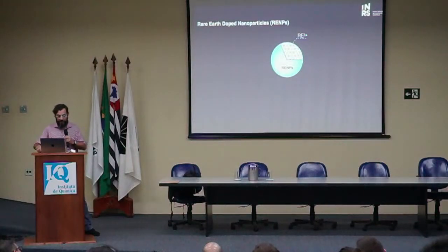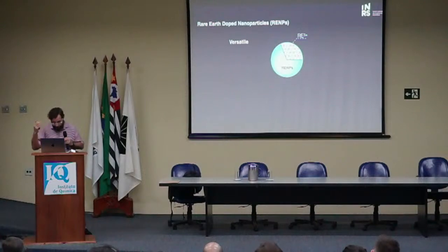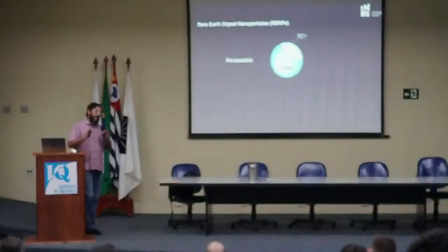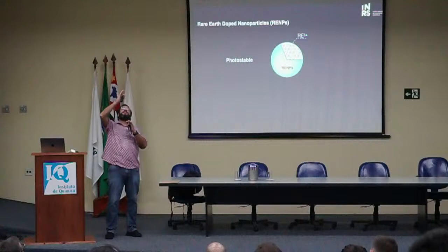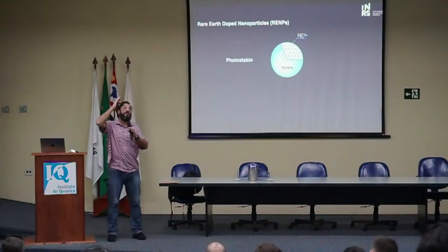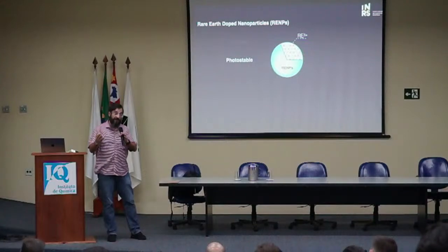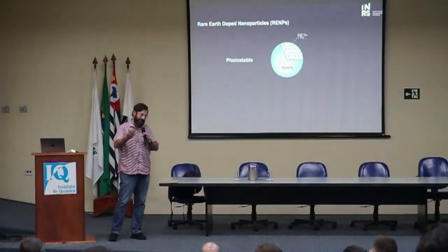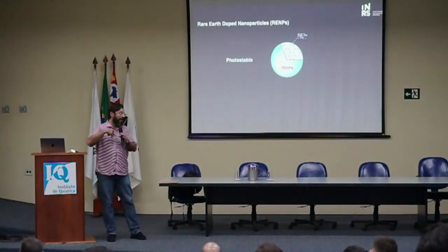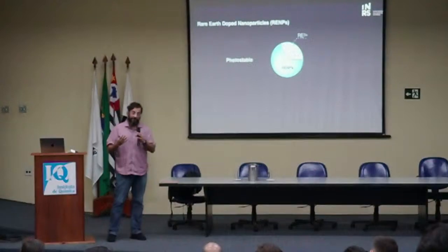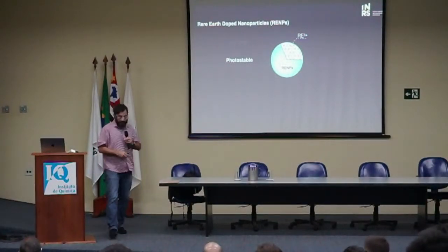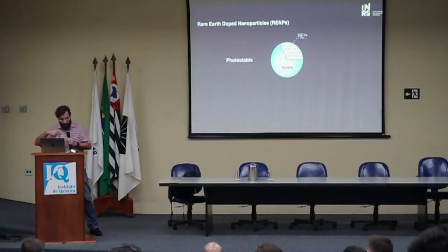So to sum up, the rare earth nanoparticles are pretty versatile in terms of their optical properties. As I showed you, we can do upconversion, we can do downshifted near-infrared emission. They're photostable. I think Fernando told me that these were changed to LEDs, but in the past, in fluorescent bulbs, you had rare earth ions in there. There are rare earth ions in lasers, and as you saw earlier, ytterbium YAG, neodymium YAG. They're used ubiquitously, they're used everywhere, so they're very, very photostable, okay? So you can pump these materials for months and years without any noticeable loss in signal intensity.